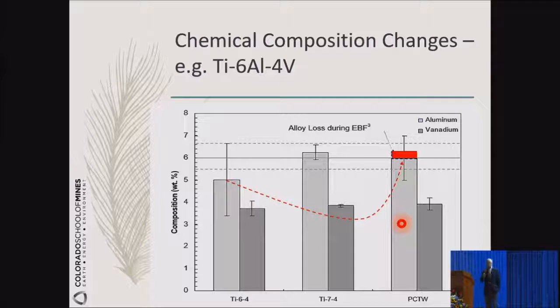But one of the major things that happens in 3D printing is that you have a composition modification, a composition change. Once you print it, you seem to lose alloying elements. So the aluminum, the vanadium seem to be lost from, for example, a Ti-6-4, titanium 6 aluminum 4 vanadium alloy. This would be the 6% nominal. If you were building Ti-6-4, you have a loss of approximately 1%, and so that is more comparable to if you had started out with a Ti-7-4, okay? So there is something that you need to learn how to work with.